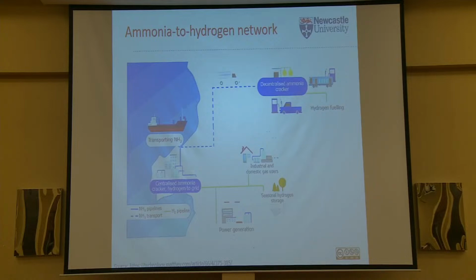This presentation is about a different way of doing that, which is a decentralized model. And this is particularly suitable for industrial clusters. Industrial clusters means that you have all the big companies in one place, most times, as it is the case in the UK, very close to the port or not very far away from the port. So the idea is that the ammonia that you are going to be receiving, instead of cracking it centrally and then supplying hydrogen, we could essentially have smaller cracking systems. So if we have 5 companies, for each of these 5 companies, you will locate a cracking system within their facilities.